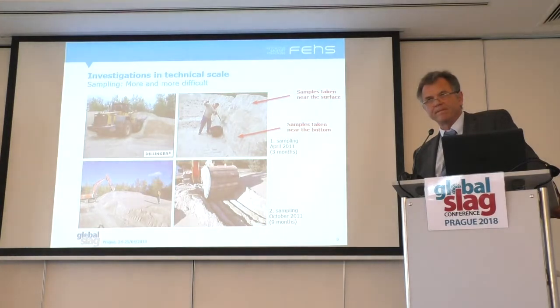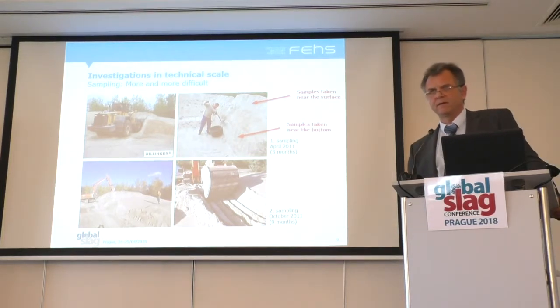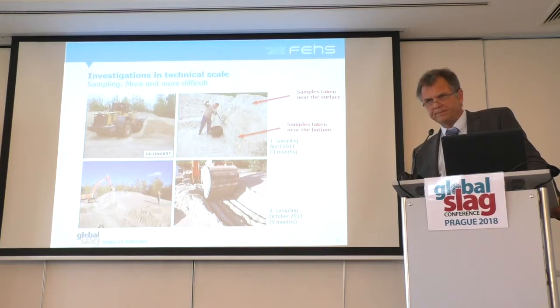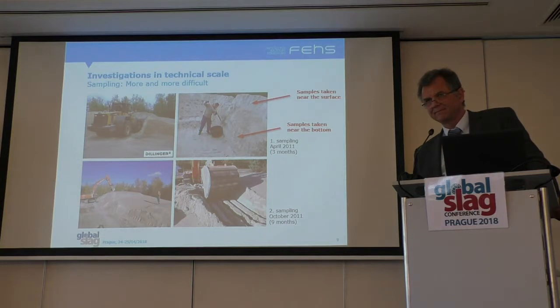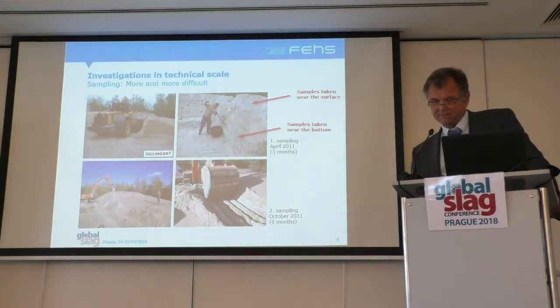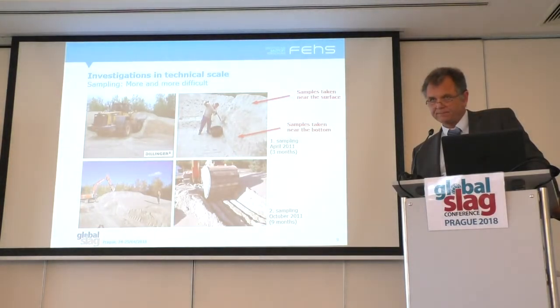My name is Zian Wu from the CHC Resource Corporation in Taiwan, and we also did some research about the storing time and the activity index of the slag powder. Because it rains a lot in Taiwan, especially in summer, we found that if we store slag powder outside, after maybe 1 year you could see the green appearance of the GGBFS. So I think the activity index is going to drop maybe 20% after you have the green appearance and after maybe 2 years of storage.